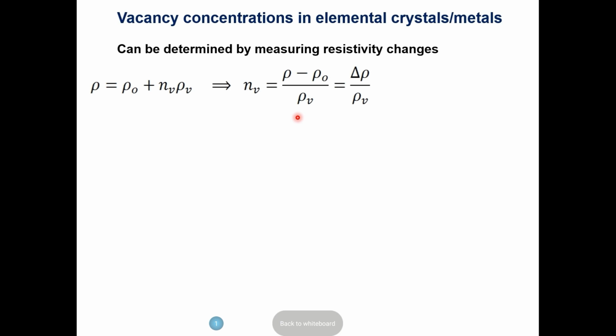Let's say you're interested in aluminum or silver. You take a thin wire of it, and all you have to do is measure the electrical resistivity to begin, such as pure aluminum with no defect. Then you heat up that aluminum sample to 700 degrees Celsius, hold it there for some time, and cool it. After that, you quench the sample to freeze in the thermal vacancies created, and measure the electrical resistivity again.